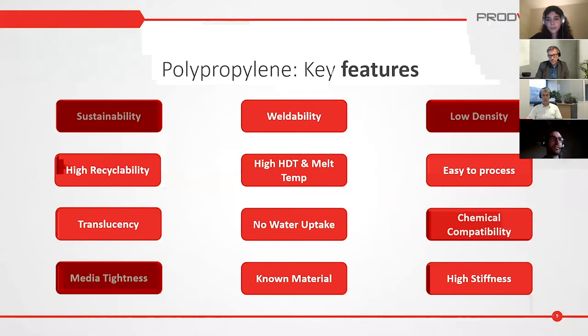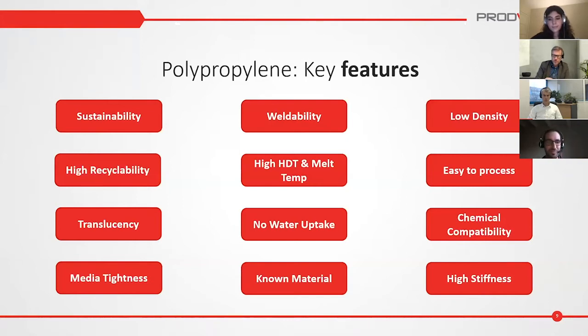High temperature, in this case high HDT, so heat deflection temperature. Just to give you an idea, the HDT-B is above 100 degrees and the VICAT A is above 130 degrees Celsius. It's easy to process, and maybe we will talk about that a bit later in the webinar. Translucency, no water uptake. This is quite interesting, and we can link that to chemical resistance and media tightness also. You can use this material with a very broad range of media, whether it's acid, basic, or water. It can be a container for such media.